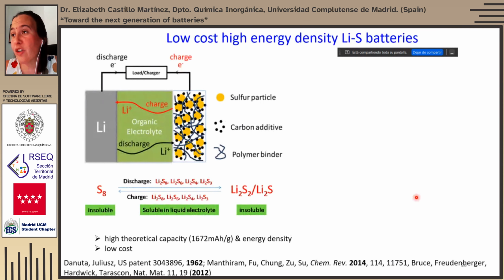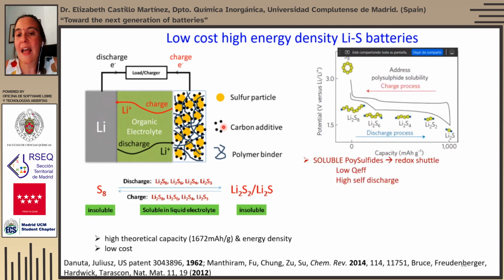But of course, these batteries also have some problems. For example, if we look at the lithium sulfur batteries, sulfur is very insulating, so you need to add a lot of conducting carbon. But also, once it starts being reduced, it starts forming polysulfides, which in the case of liquid electrolytes, dissolve. If these polysulfides are dissolved, they can travel through the electrolyte towards the lithium metal. You have redox shuttle events, which result in low Coulombic efficiencies. I mean, the battery is getting self-discharged.